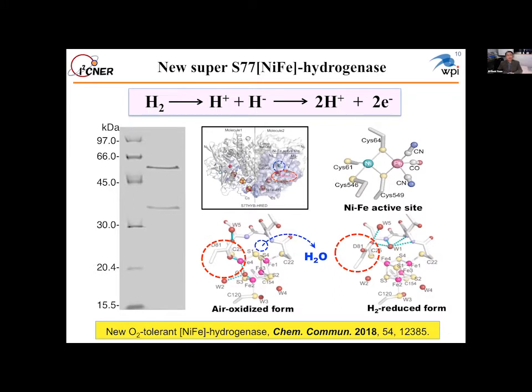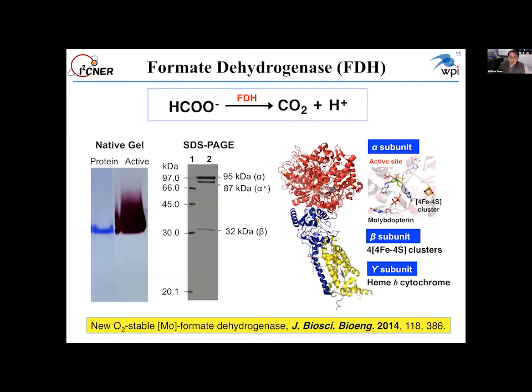To introduce this enzyme a little bit, particularly the oxygen tolerant hydrogenase we found: its active site contains a nickel ion. And what's interesting is that even if the oxygen environment changes, the iron sulfur cluster changes the redox condition and provides electrons back to the active site. It can control the activity even in the presence of oxygen. We demonstrated this mechanism. And then we found the formate oxidation enzyme.